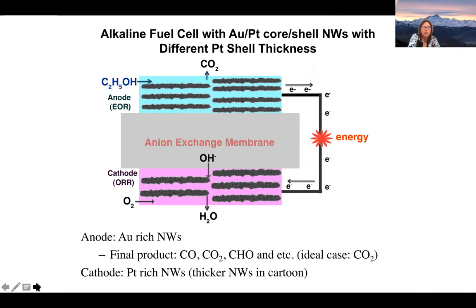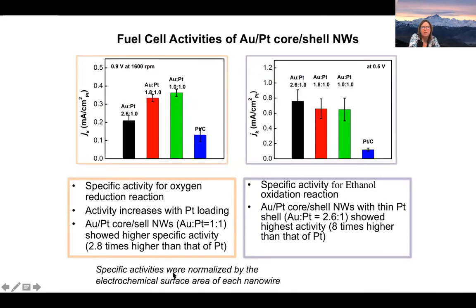I'm not going to go into too much detail of that, but basically what we're able to do is start to go in and change the sequence and change the chemical processing so that we could make a more and more efficient and high activity fuel cell. And so in this reaction here, the blue is the control. The blue is a platinum carbon electrode, and the black, the orange, and the green are going in and using biology to make different combinations and ratios of gold to platinum for two different kinds of reactions.